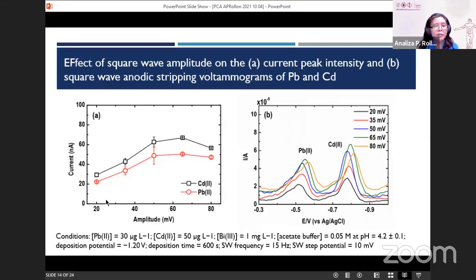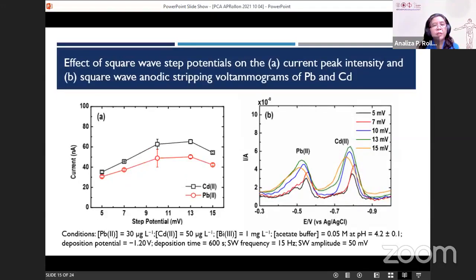we can see here that for cadmium and lead, an amplitude between 50 and 65, or even 45 to 65, maybe, is the optimum, giving the best current values. And for the step potential, we can see here that it's somewhere between 9 and 13. The step potential should be in this range to give us a good current.